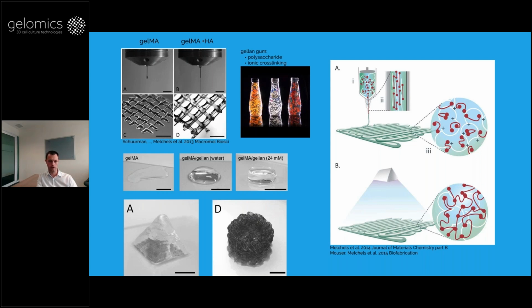That is because of the ionic cross-link between the gellan gum bonds that's broken up when you push it through the nozzle. You also get shear thinning, so it becomes more liquid to get it through the nozzle. But as soon as it leaves the nozzle, that ionic network is reestablished and it becomes a gel instantly. And then you can do a second step of photocuring, so you can take it to prolonged culture.